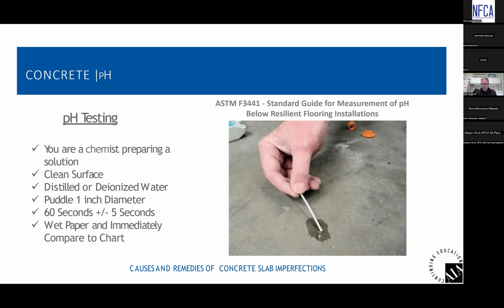So if my adhesive wants a pH of 7 or 8, and I'm testing at 12, what do I do? Call the adhesive manufacturer and get their recommendations on what to do. If the pH is too high, they may tell you we got to moisture remediate because this is what we have, or maybe they have a material that gets applied to the surface first as a neutralizer. But yeah, call the flooring adhesive manufacturer and let them detail what needs to be done in that situation.